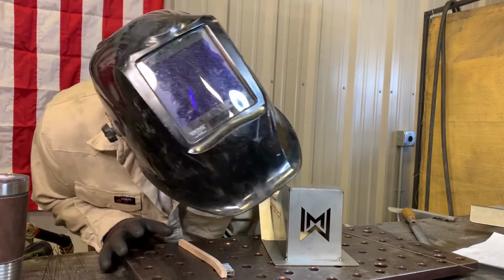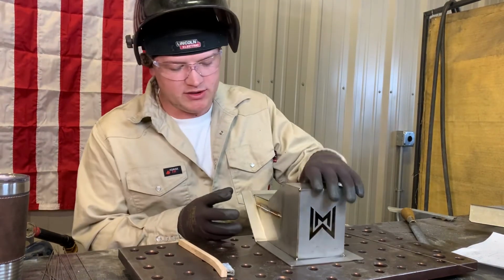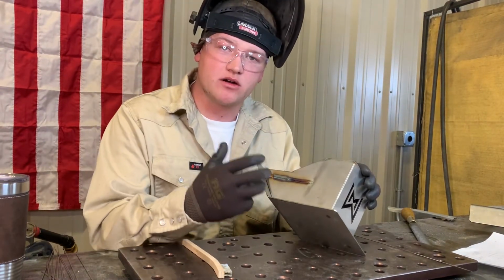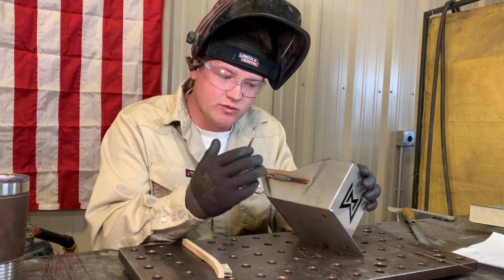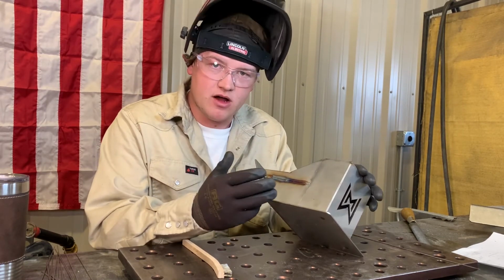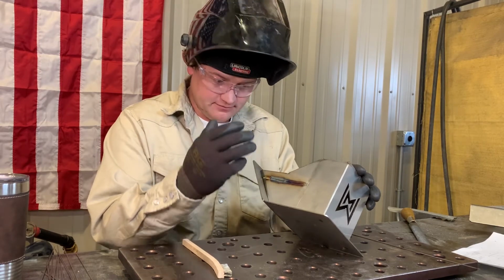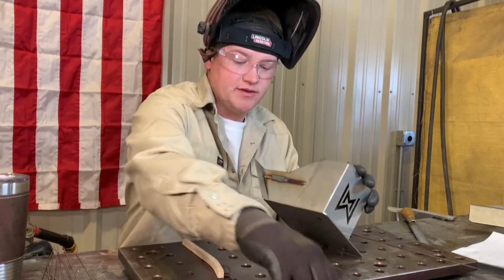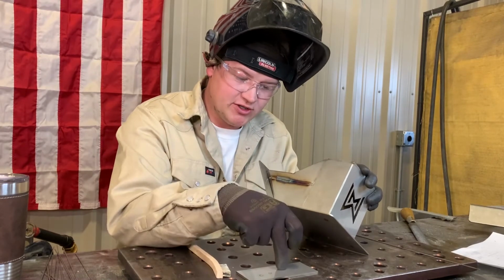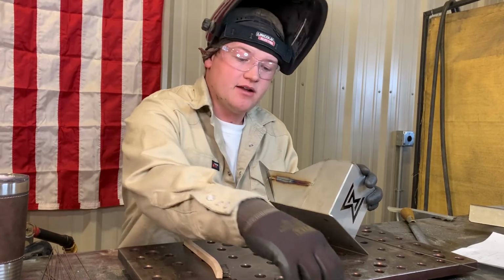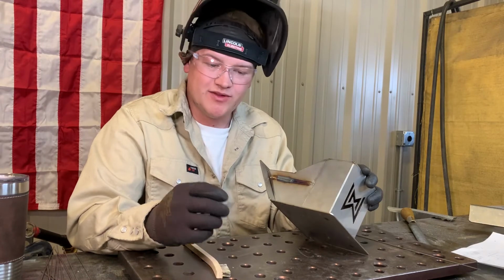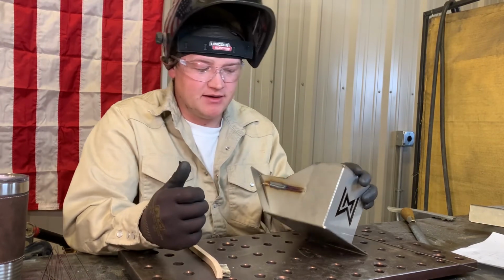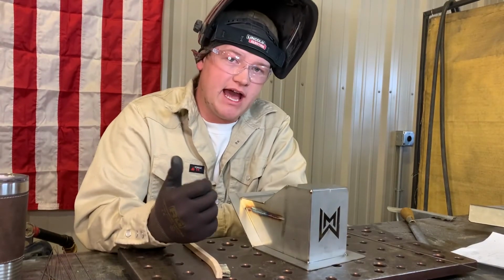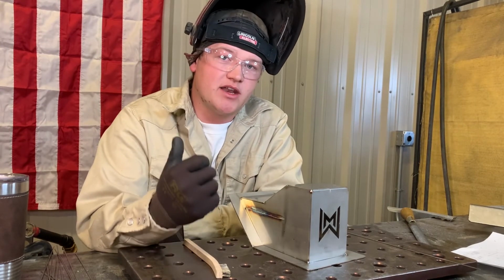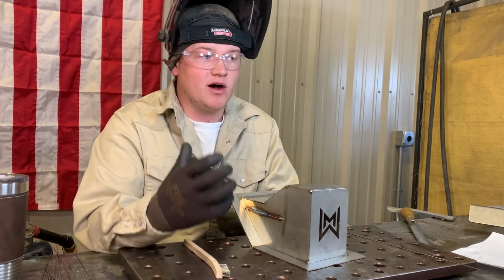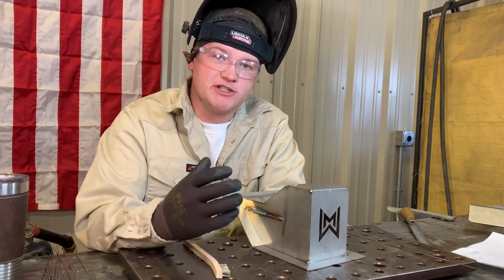So you're going to want to look at this weld you just welded and see the color of it. If it is dark gray, that means that you are having too much oxidization. There's something wrong with your shielding gas setup. So go back to the board, make sure your shielding gas is set up right, and also make sure that you are the right temperature and the right travel speed. So you can have a good setup with gas, but you can move too slow with not enough filler and make that stainless too hot, and then it's going to oxidize no matter what you do.